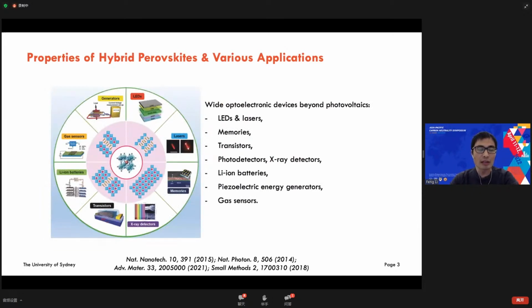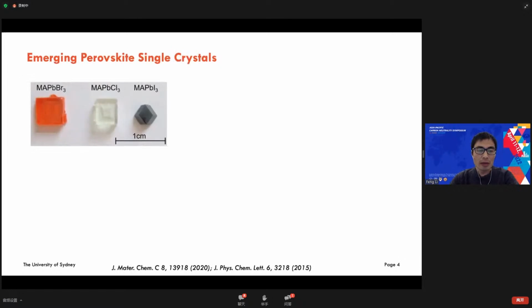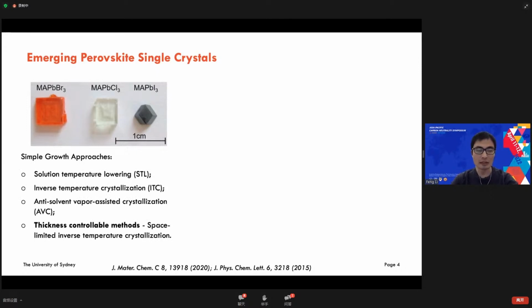Beyond photovoltaics, this material has also been used for other kinds of optoelectronic devices, like LEDs, lasers, and some electronic devices like transistors, and also radiation detectors and other kinds of sensors, like gas sensors. Except for nanostructures or polycrystals, single crystals currently attract remarkable attention, because compared to polycrystals, this material has more promising properties. It's also quite easy to fabricate single crystal perovskite. We mainly use the solution process method, and we can use a very easy way to tune the thickness of this kind of material.